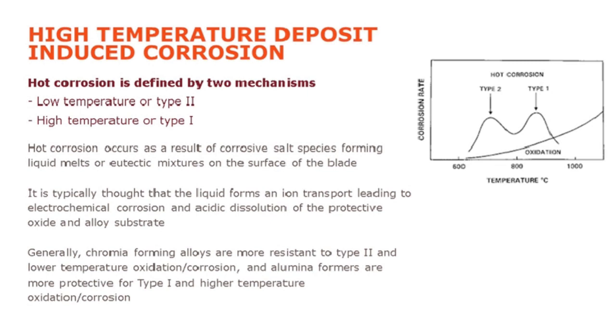So depending on your alloy composition, your coating composition, your deposit composition, you can see the temperature of these mechanisms move around. And historically, that graph on the right is often thought of as a kind of baseline, but I think in reality the chemistry is quite a lot more complex, and we probably see a more complex picture. It's typically thought that hot corrosion is electrochemical, so that liquid deposit or liquid mixture forming on the blade is an ion transport, and is enabling acidic dissolution to happen at localized locations and cause this cracking.